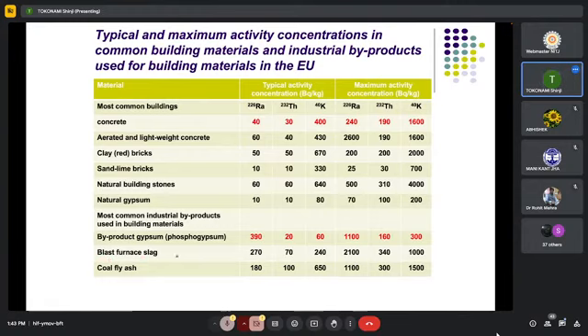Blast furnace slag, 270 for radium-226, 70 becquerel per kilogram for thorium-232, and 240 for potassium-40 as a typical activity. As maximum activity, 2,100 for radium-226, 340 for thorium-232, 1,000 becquerel per kilogram for potassium-40.